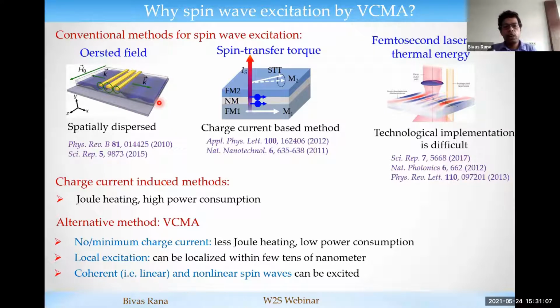That's why you cannot localize the Oersted field, and you cannot apply this method for nanostructure devices. But another interesting way is to excite the spin wave by spin transfer torque. But again, the problem is that this is a charge current based method, so it also consumes a lot of power.